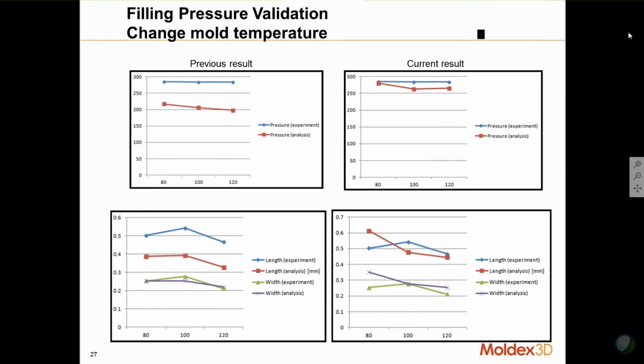The reason is that when we are doing the simulations, although the injection molding machines can drive your materials in if you just keep on adding more pressure, during our predictions, what you see here, in the top left-hand corner, is that the pressure predictions from our simulations are quite off from the experiments without taking these pressure effects on the viscosities into account. After we correct for the pressure effect, it is much closer. And this has a few significant impacts. First, it will help you to do more accurate dimensional predictions. The reason is that during the packing phase, if the packing pressure is not correct, there is no way that you can estimate how much material is being squeezed in during the packing phase. In this case, your PVT is not correct, and the warpage prediction is not correct.